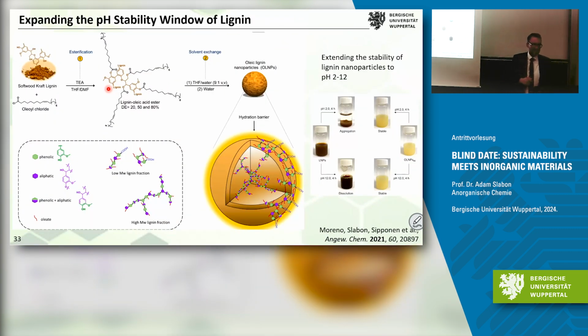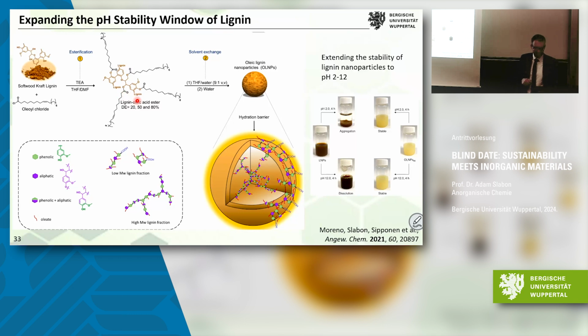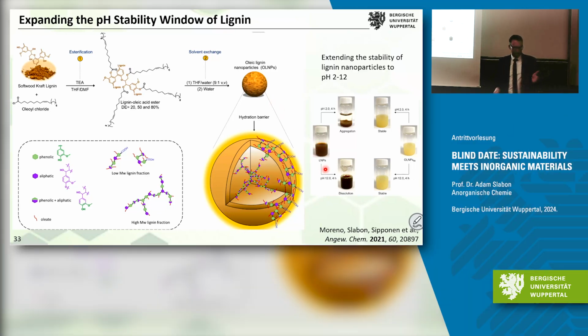The problem is the stabilization. We found you can stabilize the lignin also with organic chemistry by making an esterification reaction. You make it more hydrophobic, and then you can precipitate it out as a nanoparticle in solution. This expands your window of application. Here you have pure lignin at pH 7; at pH 12 it dissolves, so it's not a template anymore.